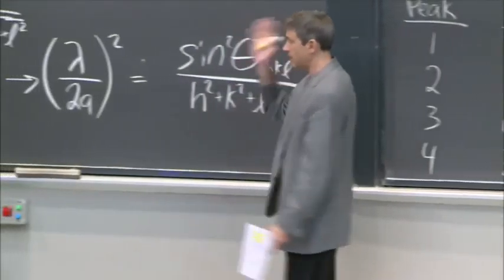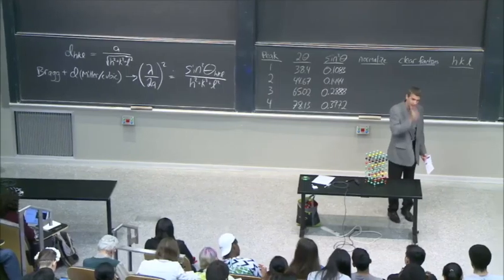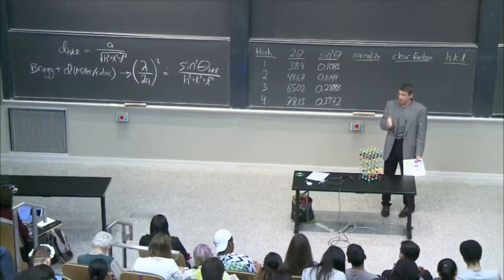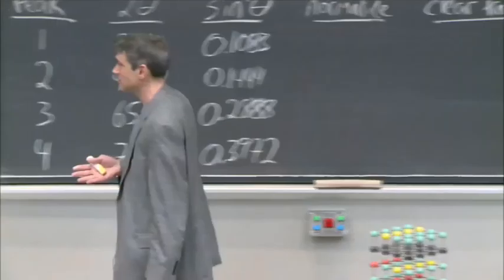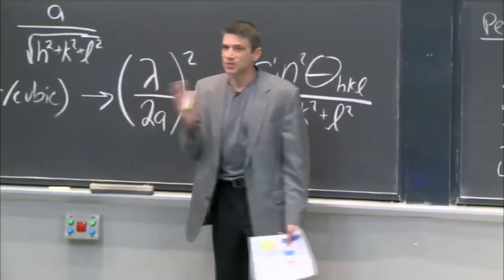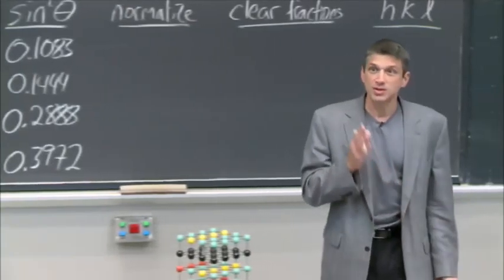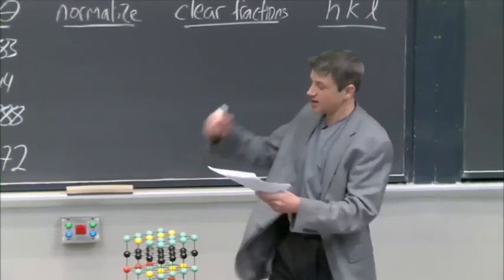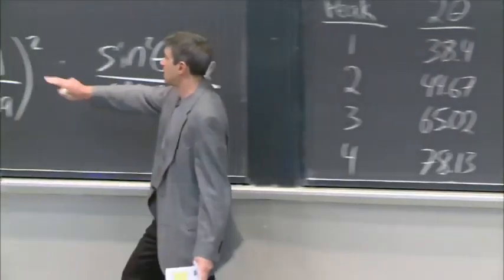And so we said, well, that's the whole beauty of these characteristic X-rays, because if you take a K alpha line from copper, it's always 1.54 angstroms. It's always lambda equals 1.54. That's what's so nice about it. It doesn't depend on anything else, just the metal you put in there as the target. And it's called a target because you're targeting it with electrons. So the copper target, K alpha, lambda constant.